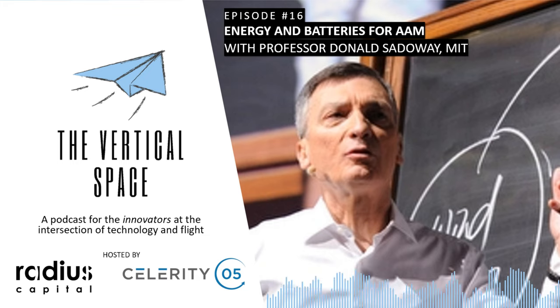And then if you get into something more energy dense and with higher lithium capacity than the shop-worn transition metal oxides, the cobalt oxide, nickel oxide, manganese oxide, then you could start seeing a major jump in energy density. Some of what I see is people trying to substitute the graphite-based negative electrode in the lithium-ion battery with lithium metal, but they don't think about what's happening on the other side. You can't fully lithiate cobalt oxide or nickel oxide. There's a limited range of lithiation.